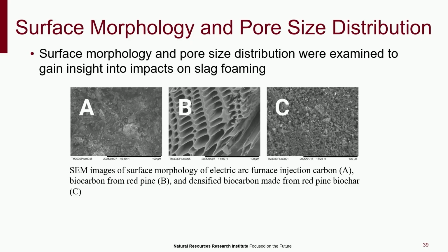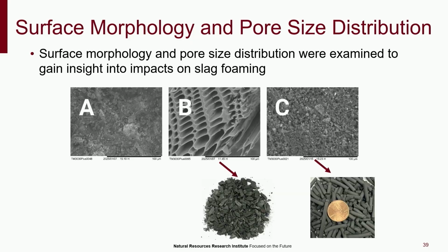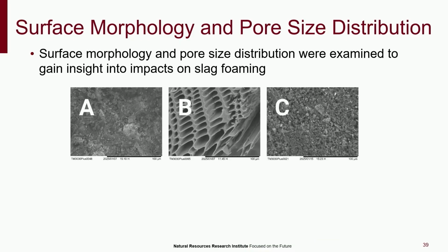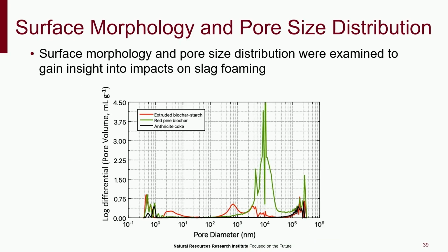But we already saw these SEM images, so this is just injection carbon used in the industry. This is our biochar before densification, and then our biocarbon after densification. Again, some images to correlate. And then this is a pore size distribution. We have a kind of a unique pore size distribution.